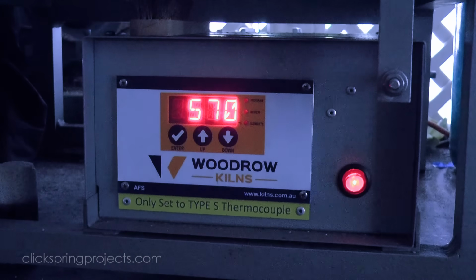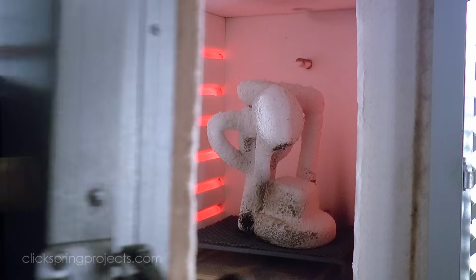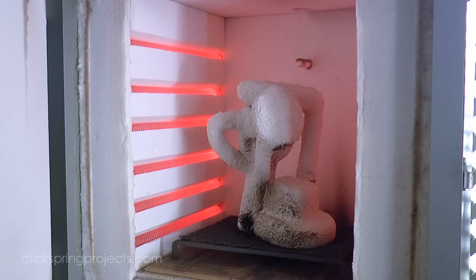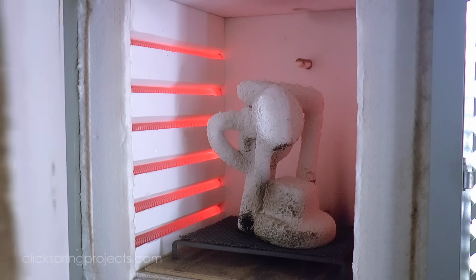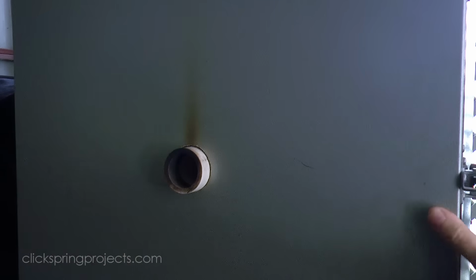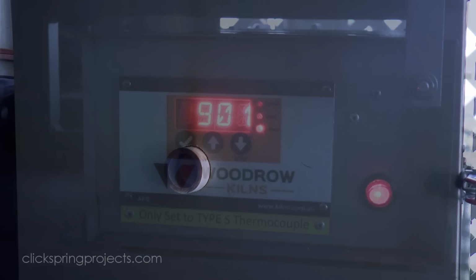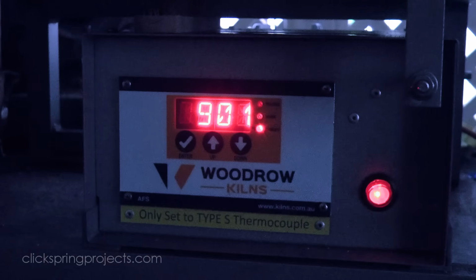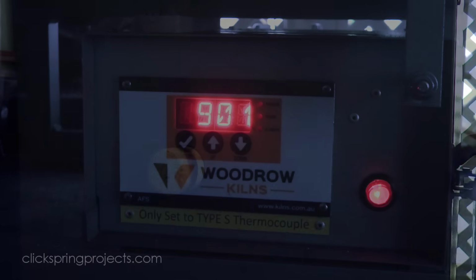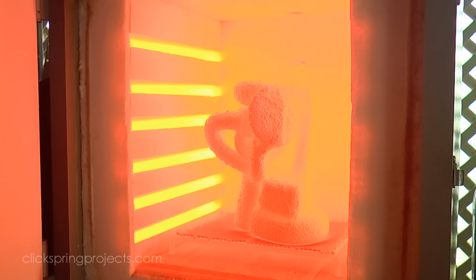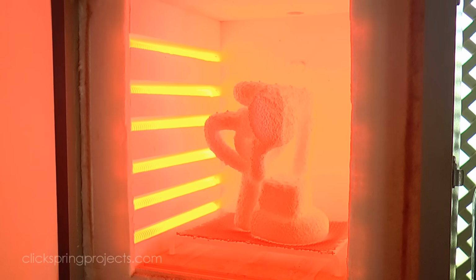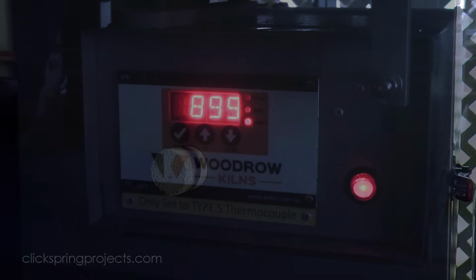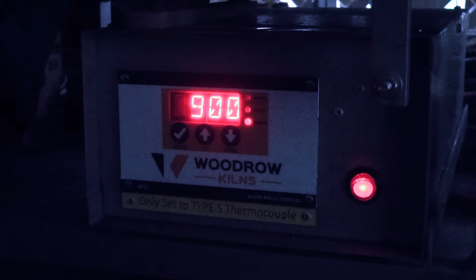Another ramp to 570 Celsius for an hour or so, and the remainder of the printed elements break down, and the soot residue is starting to disappear. The kiln is then taken to 900 Celsius for 3 hours to bisque fire the mould. After which it's left undisturbed overnight to cool to room temperature.